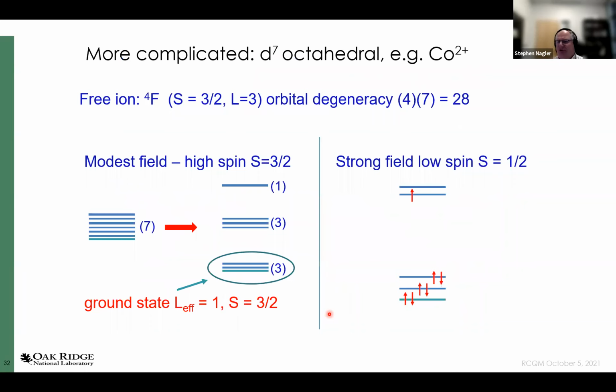So I also want to mention one other slightly more complicated system, which is 7 d electrons, exemplified by cobalt 2+. Now this is an F state, which is orbitally degenerate, not 5-fold, but 7-fold. And if I put that in an octahedral field, I assure you it doesn't split into a 3 and a 2. It splits into a 3, 3, and a 1. And for this case of 7 electrons, that means the ground state manifold, if I don't have a super strong crystal field, is going to be L effective equals 1, S equals 3/2. There's also a possible low spin state, which has spin a half. But usually one ends up with this sort of weak or intermediate crystal field scenario.